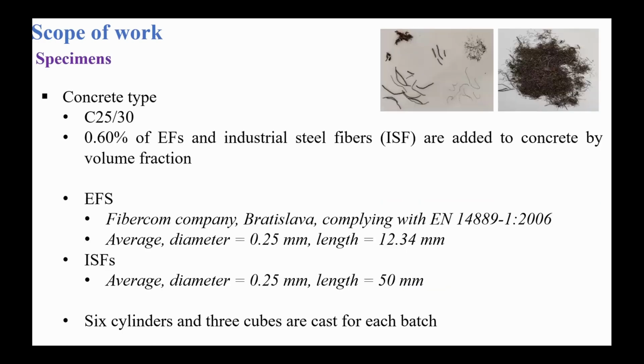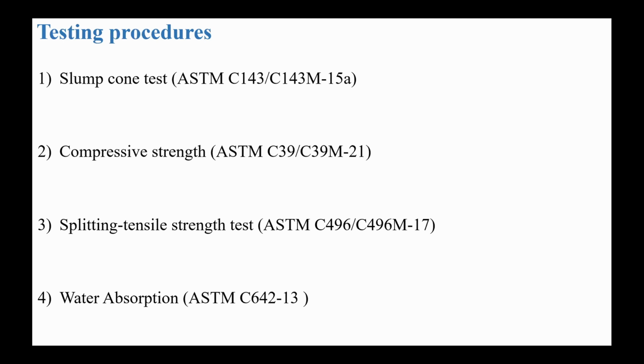The scope of the work is that we used the concrete which was available. We designed our mix according to C25/30, and 0.6% of recycled fibers were used, and 0.6% of industrial steel fibers were used as a reference. These were added by volume fraction. The locally available fibers were provided by Fibercom company, and these are the dimensions of the recycled steel fibers, and below are the dimensions of the industrial steel fibers. In total, 6 cylinders and 3 cubes were prepared for each batch. ASTM standards were followed for each test, as shown here.